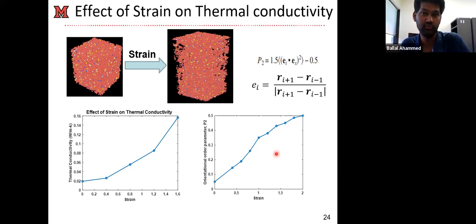So how can we actually tune the thermal conductivity? One way to tune the thermal conductivity is to apply strain in the material. As I mentioned, in a single chain, we found that the thermal conductivity is 2 orders of magnitude higher than the other cases. That means it's something related to the straightness of the polymer chain. In our case, when you compress our system, we know that our polymer chain is very curled up in space. So when the phonon propagates in those polymer chains, they get scattered from here and there.